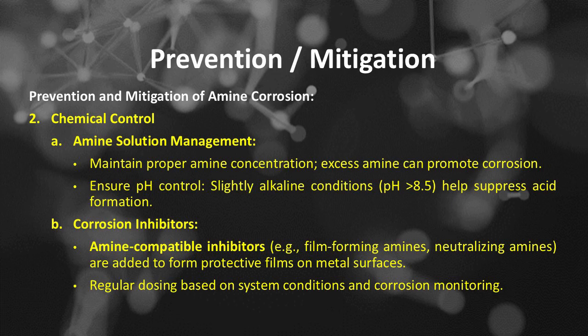Prevention and mitigation of amine corrosion. Number 2 is chemical control, includes, number A, amine solution management, includes, maintain proper amine concentration. Excess amine can promote corrosion. Ensure pH control. Slightly alkaline conditions, pH greater than 8.5, help suppress acid formation. Chemical control. Number B is corrosion inhibitors, includes, amine-compatible inhibitors, such as film-forming amines, neutralizing amines, are added to form protective films on metal surfaces. Regular dosing based on system conditions and corrosion monitoring.